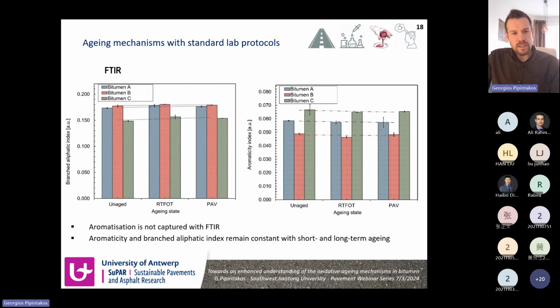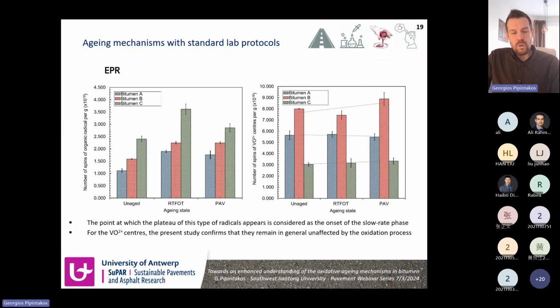Additionally, we observed that from the FTIR spectra, if we isolate the branched aliphatic functional groups and the aromaticity index, these were almost unaffected by aging, since this was stable, as you can see. So this means that the hypothesized aromatization that hydroperoxides could have cannot be captured with FTIR. For that reason, we later also used electron paramagnetic resonance in order to see how the radicals can be captured.